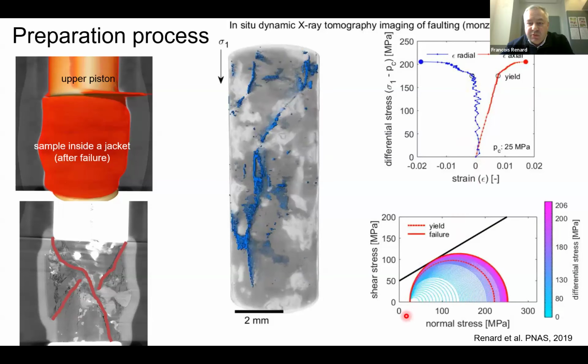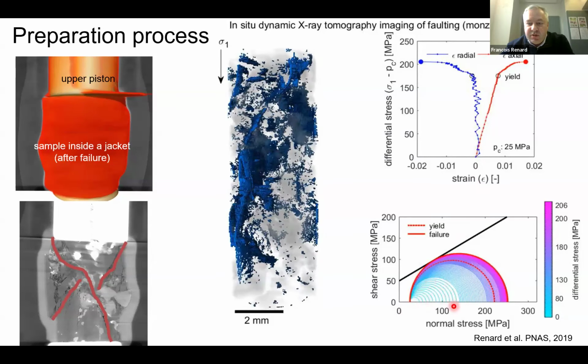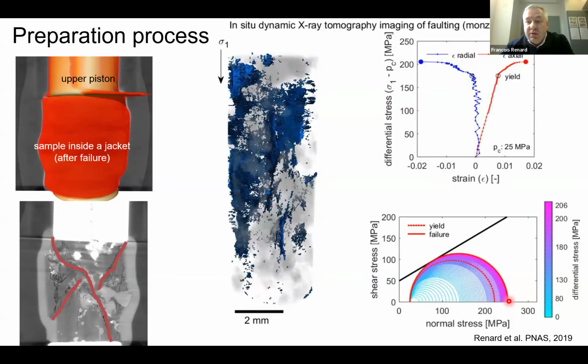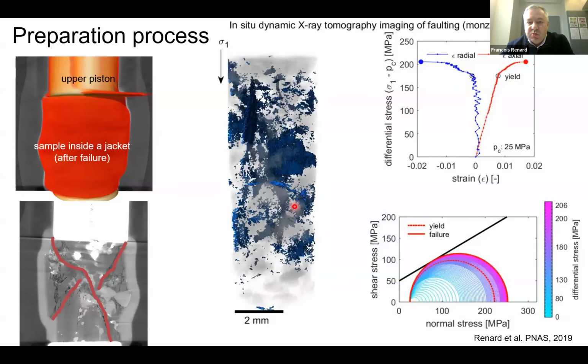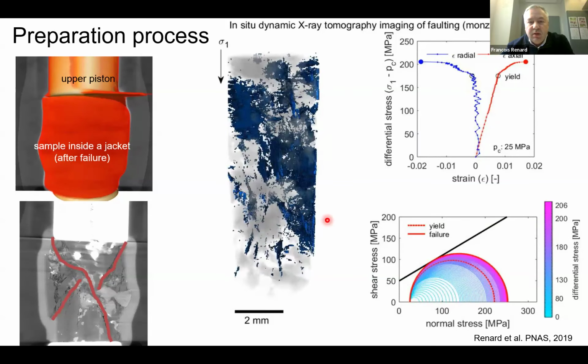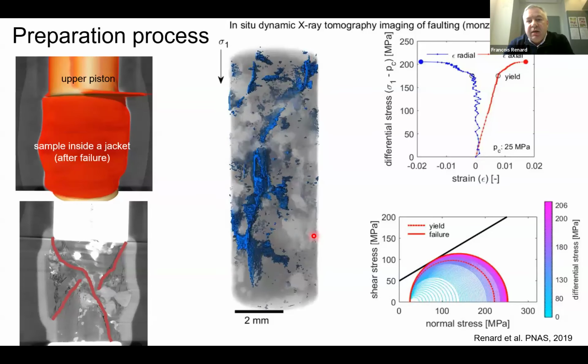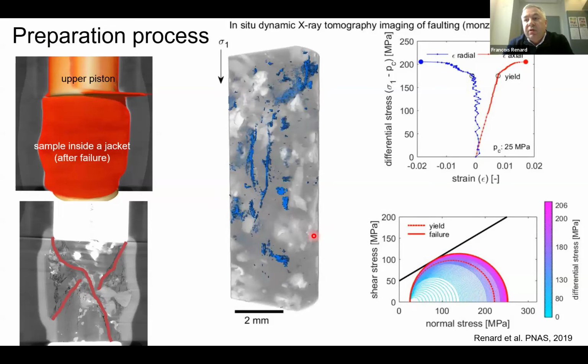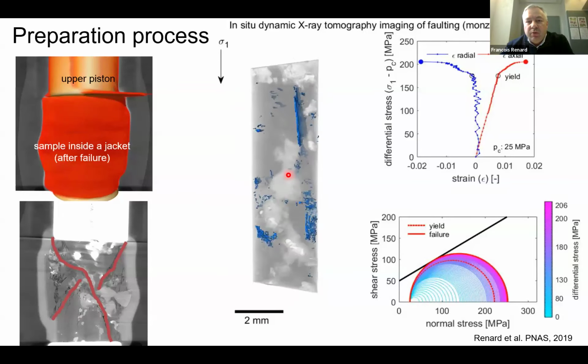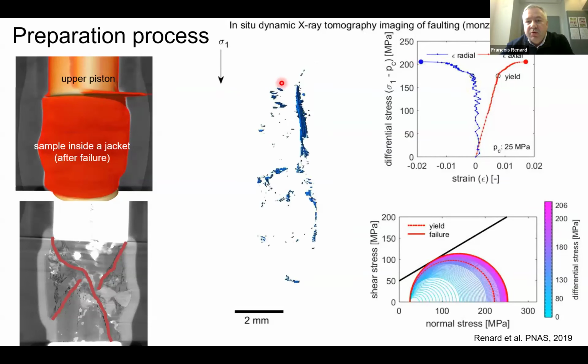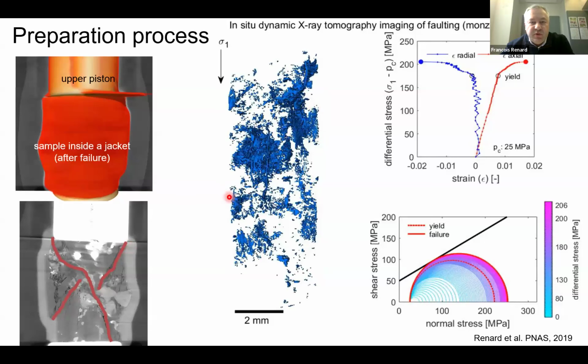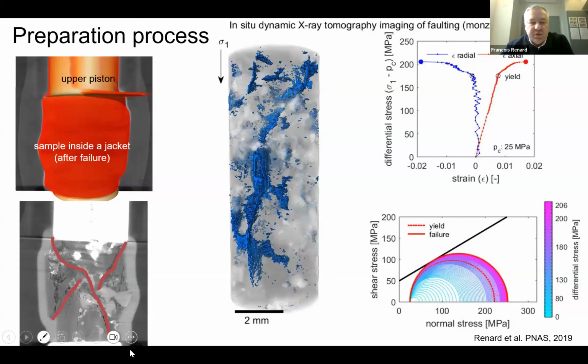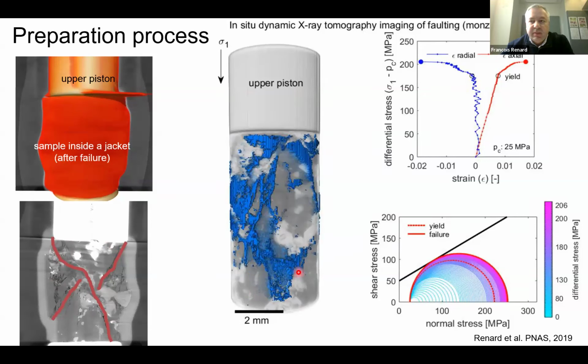And this sample is loaded. So I put a Mohr circle for the geologists here. So this sample is loaded by increasing the axial loading. That's why we have different circles, and each circle corresponds to one of these 3D volumes. And here, that's the sample at 99.95% of the stress at failure, so just before it fails. On this sample, when 0.1 megapascal is added to the curve here, the sample will fail. And when it fails, you will see it at the end of the movie, the sample collapses, producing these two conjugate faults. That's the sample here that has failed. So with this data, we have a 3D image of a rock sample every 6.5 micrometers in 3D as a function of time.